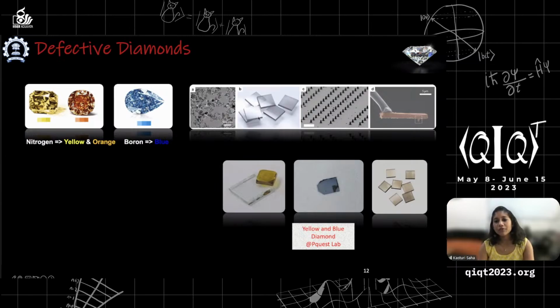Now in the lab, of course, you can grow diamond, and this has become a very nice technology, with CVD or HPHT methods of developing diamond. You can see that they essentially look like glass plates. These are CVD grown plates, and the plates can then be crushed to form what are known as nano diamonds. You can also use the plates to lithographically develop pillars, which you can attach to an AFM to form the scanning tip, etc.